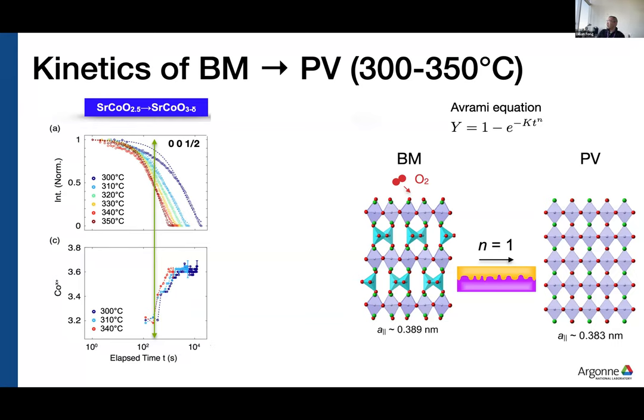So you're turning on oxygen at 300, or between 300 and 350. Oxygen comes in at the top. It has to break apart into atomic oxygen, enter the lattice, and it's essentially propagating from top to bottom, which makes sense.